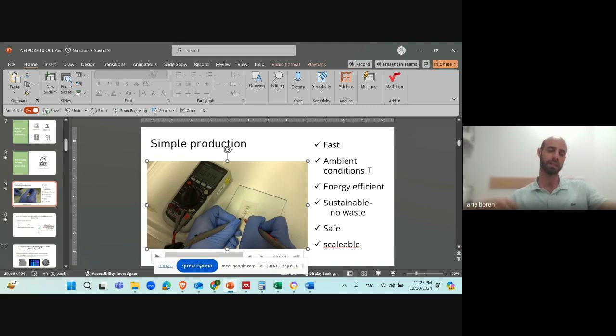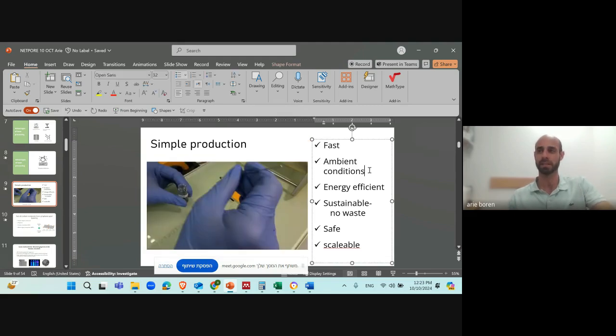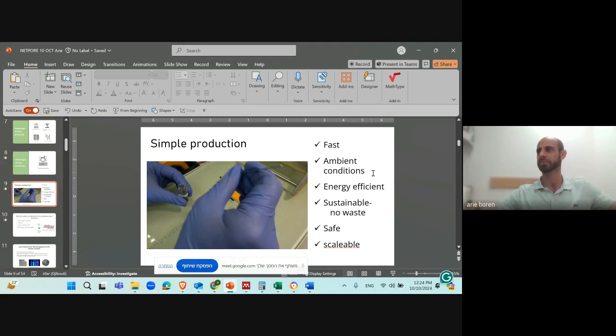But with the laser, the reaction is so fast, it's happening in milliseconds, so that the oxygen is eliminated and the exposed carbon just forms a very fast bond to whatever other carbon is next to it instead of oxidizing. Okay, so the kinetics of the graphitization in this case is faster than oxidation or burning of the carbon, and this is why it can be done in ambient condition.